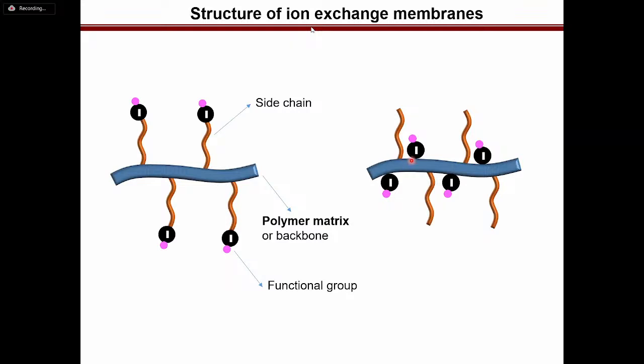However, we will not say directly that this base material is also very good for stability. It is very important to control the stability of the membrane. For example, I work with SPEEK, sulfonated polyether ether ketone. SPEEK membranes are very well studied in fuel cells, and this kind of backbone is known to be very stable, mechanically stable and conductive, and also heat resistant. If you use some other type of polymers like PPO or others, maybe they are not as stable as SPEEK membranes.